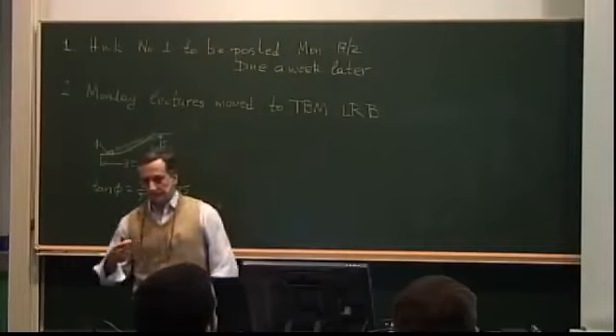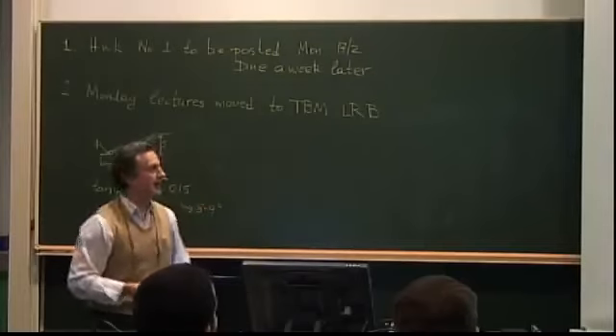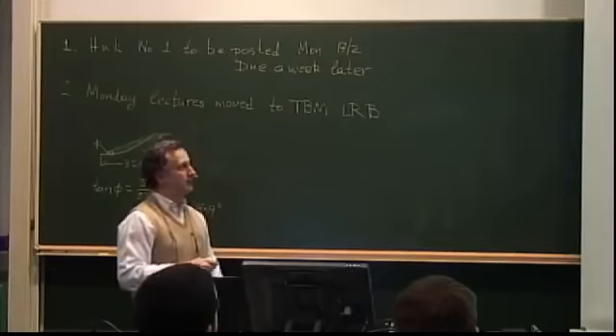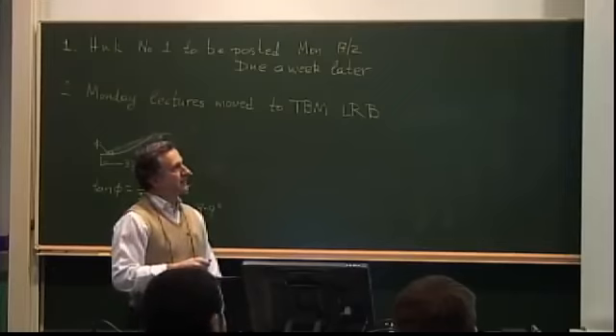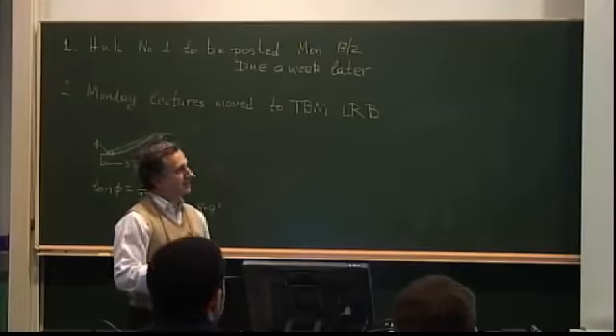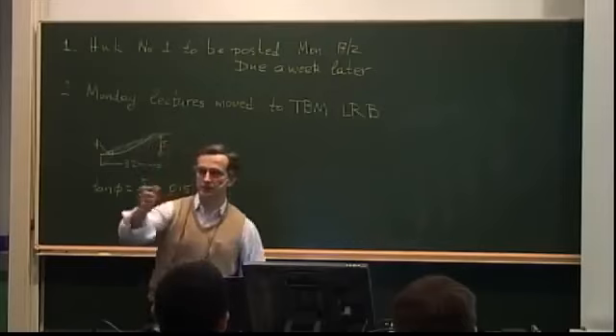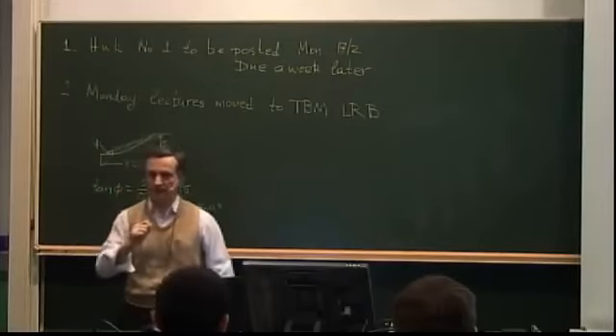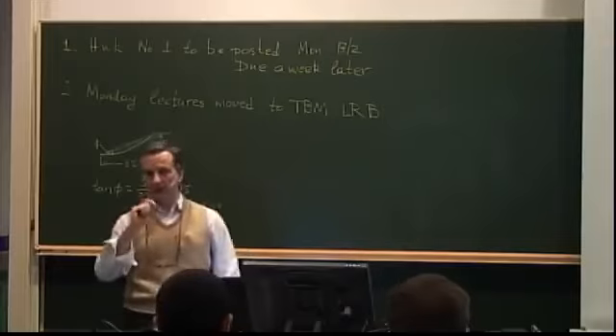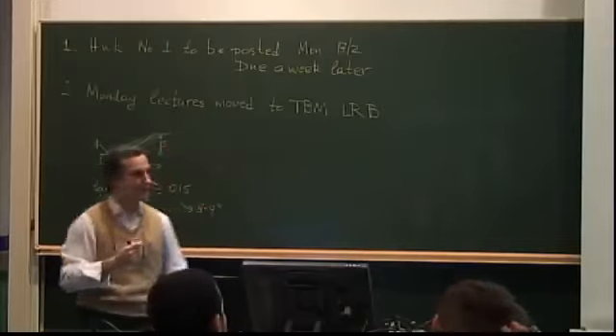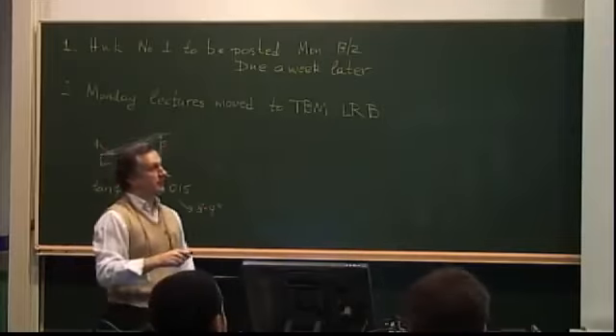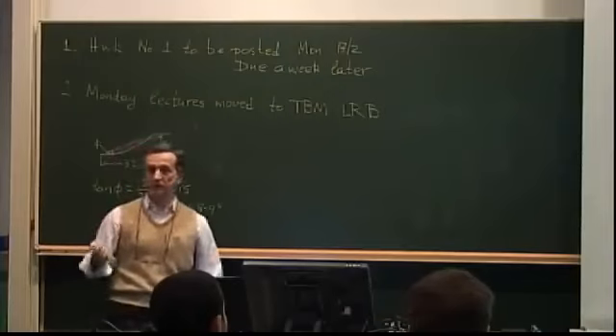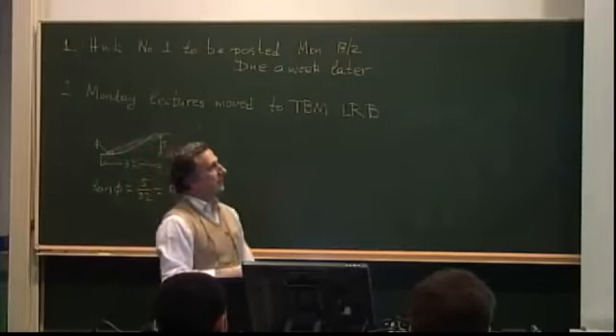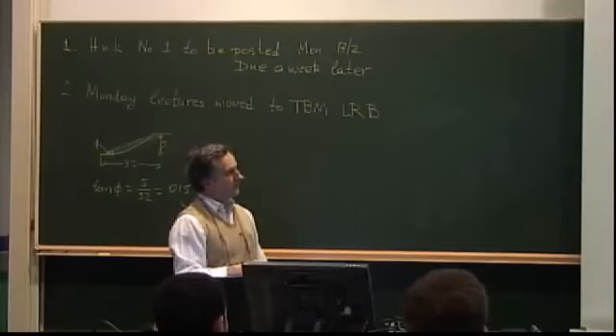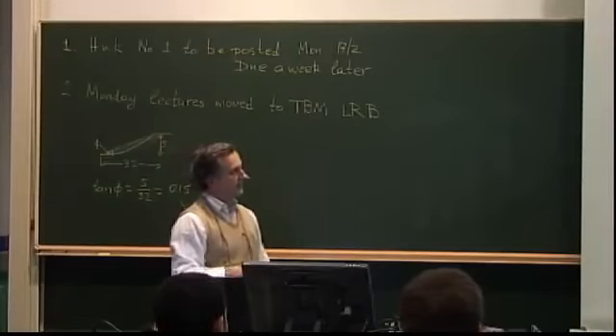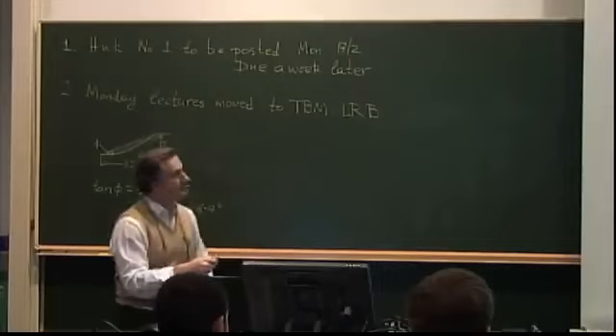Then there was a generalization that Steve Tsai and Ed Wu did, which said, okay, this really doesn't recognize the fact that I can have different tension strength and compression strength in a composite, while, as I said, in metals those tend to be close enough that you can use a single value. So let me now introduce the XT and XC, which are the individual tension and compression values, and the YT and YC for transverse, and the S value here. Now this criterion becomes this one.